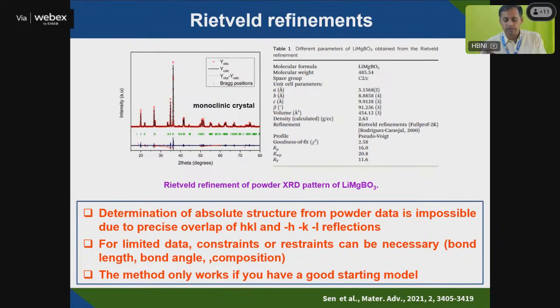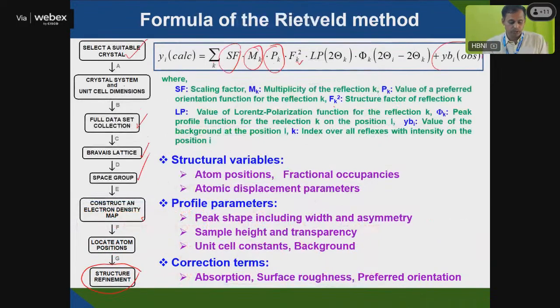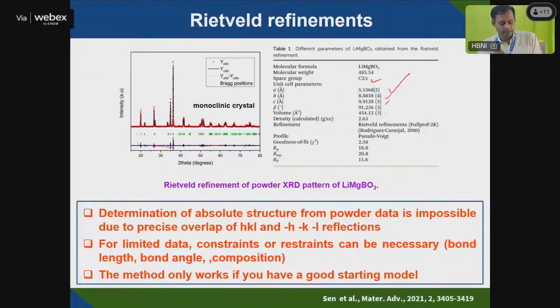You can get the difference. From this analysis you can get lattice parameters A, B, C, and then the volume, density, all those information, and you can identify the space group. Here it gives you structure variables: you have to provide atom positions, profile parameters, and different corrections. So finally you will get this. Determination of an absolute crystal structure using powder is quite difficult, mostly impossible, because you have HKL and minus HKL reflections. So for limited data, constraints can be necessary, like bond angle, bond length, and bond composition. If you get some information, that will help you with the starting model, and you can identify the proper crystal structures.